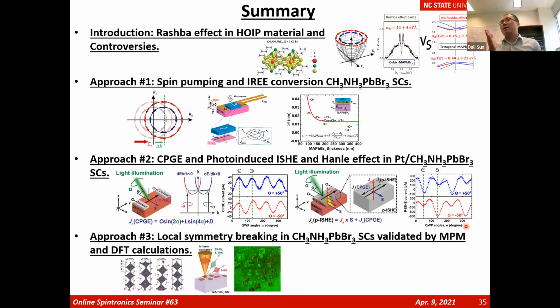So is there a debate about the Rashba state in hybrid perovskite? Yes. The reason is the Rashba state forms locally depending on the termination of your single crystals. Both sides are correct. There is a Rashba state existing. There's also a possibility of not being able to observe the Rashba state. That's because it forms locally and has to be detected by a spatially resolved method like the second harmonic microscope or photo-induced ISHE effect, as we demonstrated here. Hopefully, our work will solve the controversy in this field and provide a new way to design hybrid perovskite for a large Rashba effect in these solution-processed semiconductors. So that concludes my talk.